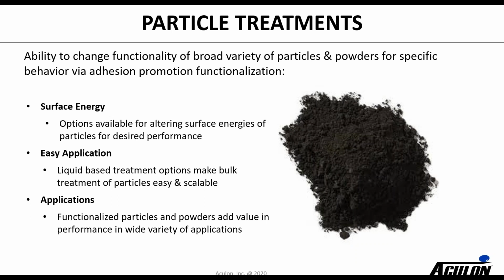And particles, we've got some. Basically any metal oxide or even some polymeric particles we can modify, and we can either alter their surface energy to improve the interaction between them and others, either resin or wherever they're being used. Most of the time it's an easy application. You can just suspend the particles in a coating solution, stir it, and wait for it to react, and then either filter or just remove the particles and then use them in an improved way. And so there's a lot of different applications for that, whether it's just filled paints or adhesives, or whether it's functional particles in a catalytic system.